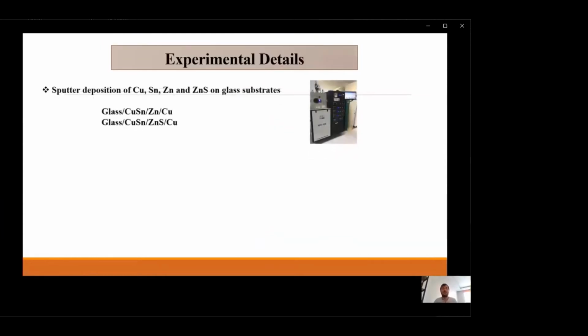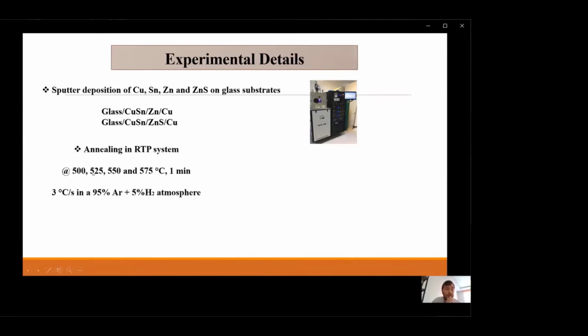What were the experimental details? We sputtered the metallic film layers one by one with a PVD system in our laboratory to form these two stacking orders, copper-tin-zinc-copper and copper-tin-zinc sulfide-copper. We annealed them in the RTP system at 500, 525, 550, and 575 degrees for 1 minute, because the RTP gives such a nice facility with a heating rate of 3 Celsius per second in an argon and hydrogen atmosphere.